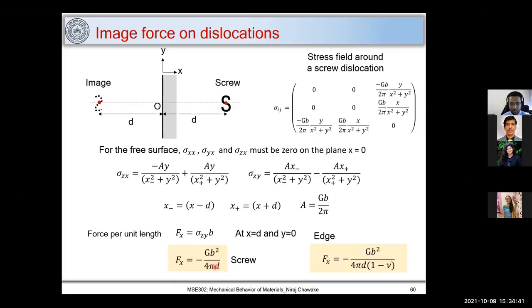So D is nothing but the distance of your dislocation from the surface of your sample. You know your material, the Burgers vector, and the sample thickness, and you can find out what the force acting can be. Now, you can compute the Peierls-Nabarro stress as G exponential of minus 2 pi W upon B. You can refer to any standard physical metallurgy book and you can get this relation.